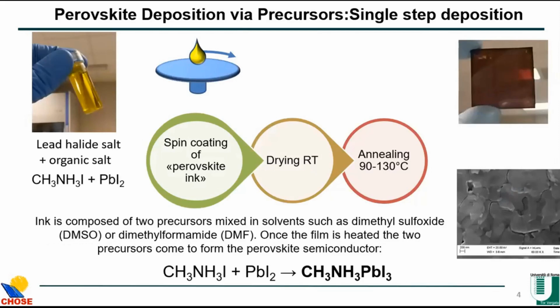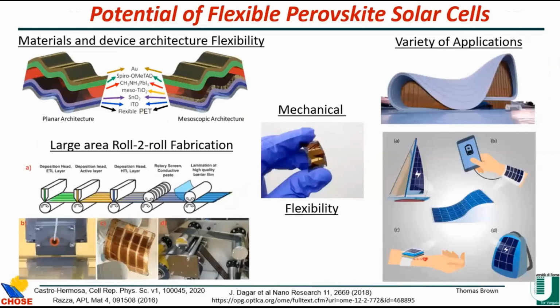Perovskite solar cells are solution processable, and you can deposit them through a precursor ink. The main technique is spin coating, of course, in the labs. Then you dry and anneal it around 100 degrees, and it converts to the final perovskite layer. This is methyl ammonium lead iodide, and this crystallization process is key to obtain high efficiency solar cells. And you can go flexible by using substrates like PET, but also even paper or other types of devices.